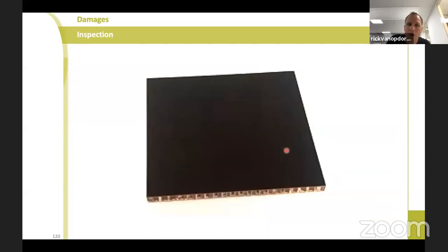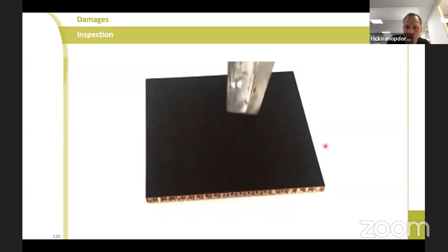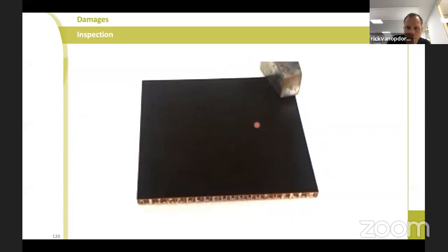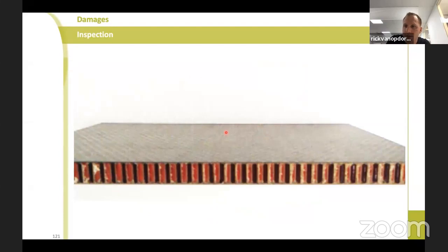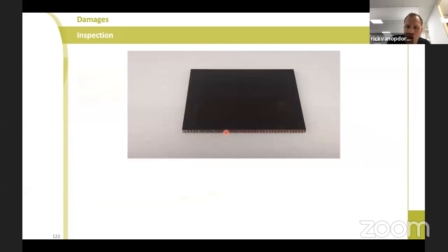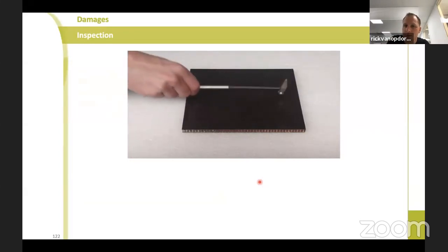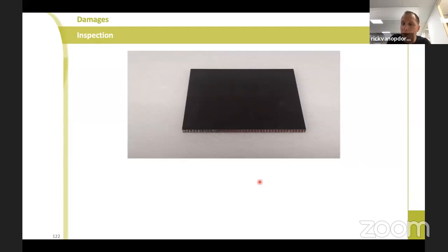We do the same on a composite panel, only 3 layers of carbon fiber and honeycomb. And what you see is nothing. So if you compare that with the metal part, the problem is that the damage is there. So this is the tapping. What you hear is the damage. So even though the damage is not visible, the damage is there. So that's a big difference nowadays, and a problem with composite versus metallic materials.